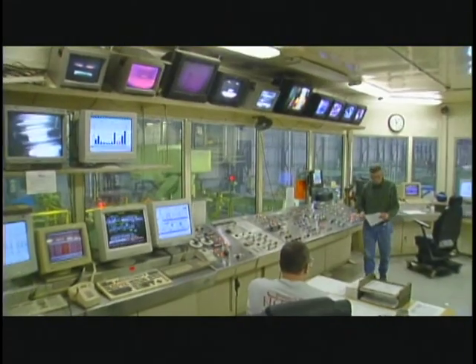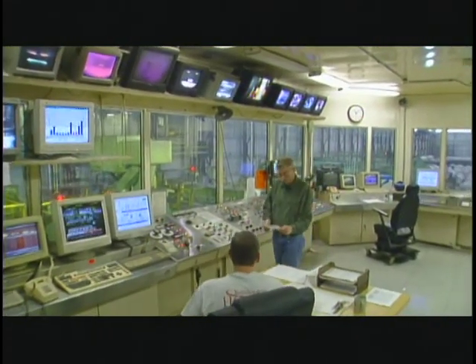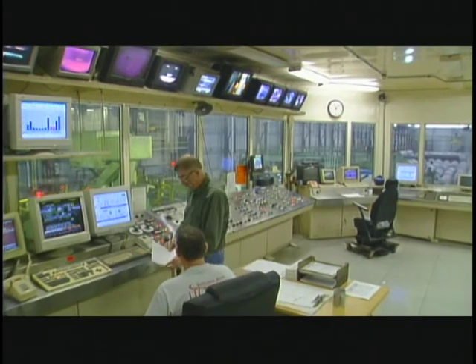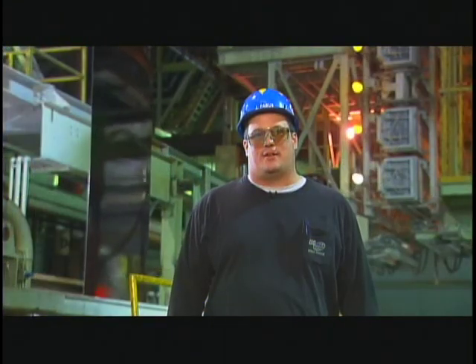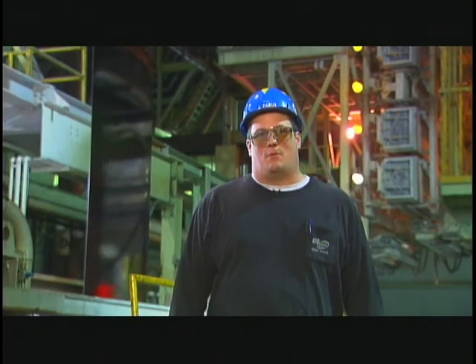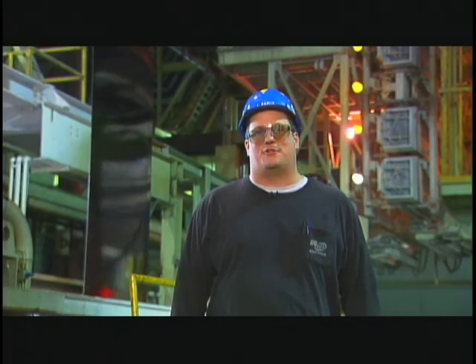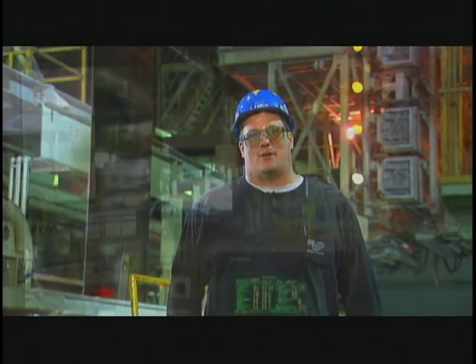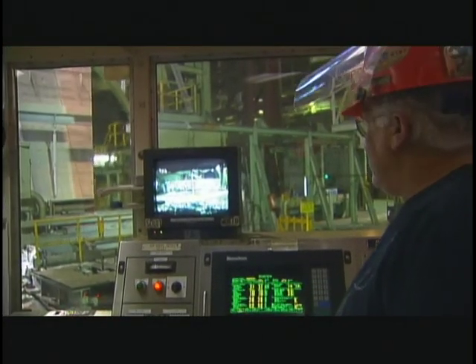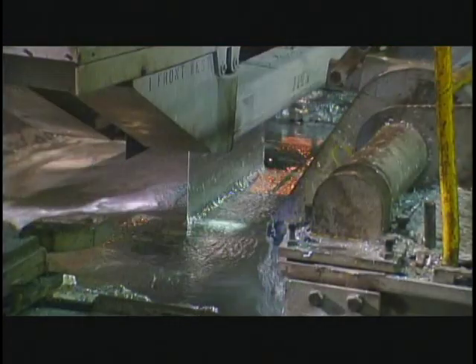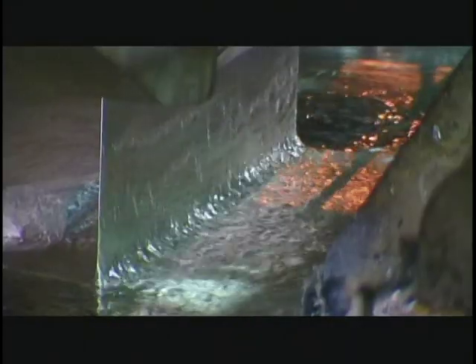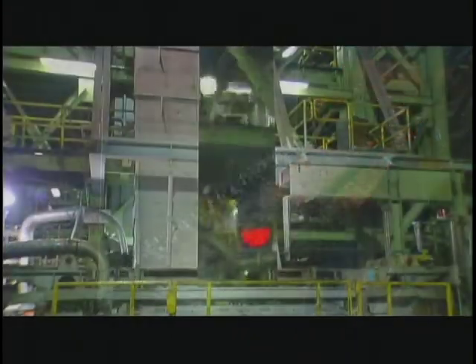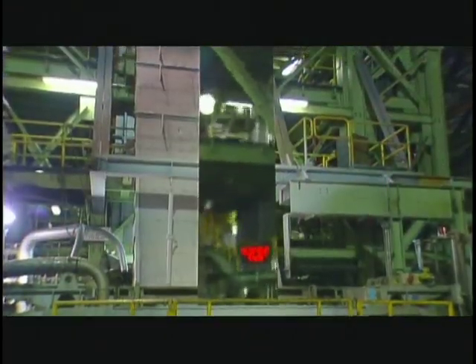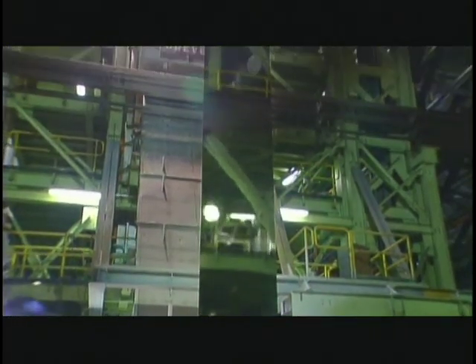Initially, the coils are charged into the hot dip line, and they are cleaned to remove any iron fines on the material. Then the strip comes into the annealing furnace, where it is annealed to peak metal temperature to get the formability characteristics the customer desires. The material then is run through the zinc pot. It'll be coated to a specific coating weight depending on the customer's requirements. The strip is then cooled down to ambient temperature.